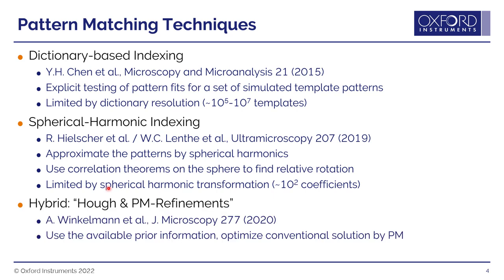A slightly different approach that hasn't really been given a universal name — but we're calling hybrid pattern matching — has been put forward in a number of papers, including one in 2020 by my co-author Armin Winkelmann. This is where the process uses the available prior information, typically from Hough indexing, and then optimizes that solution using pattern matching. That's what we're going to focus on primarily during this presentation, and hopefully I'll show you just how beneficial this approach can be.